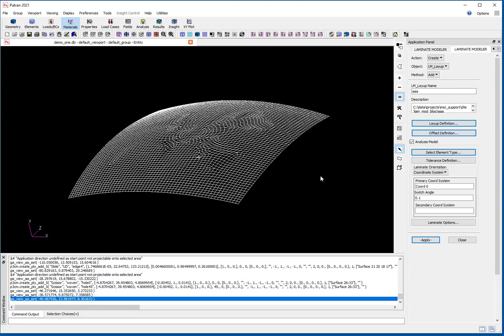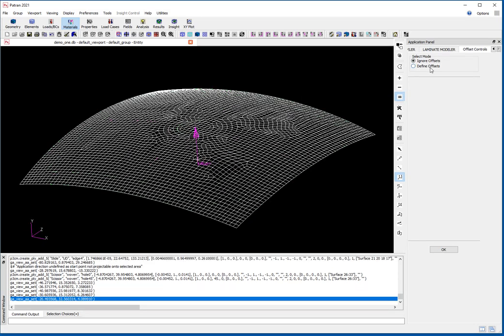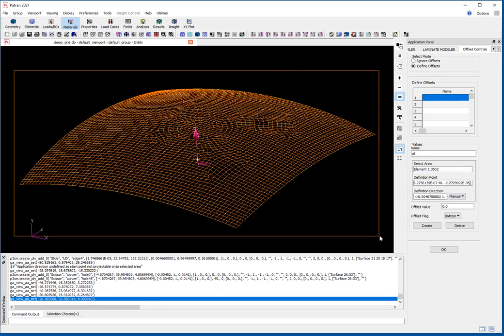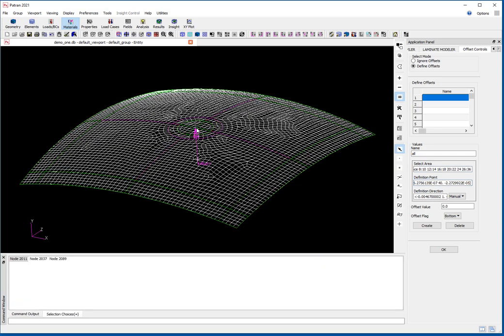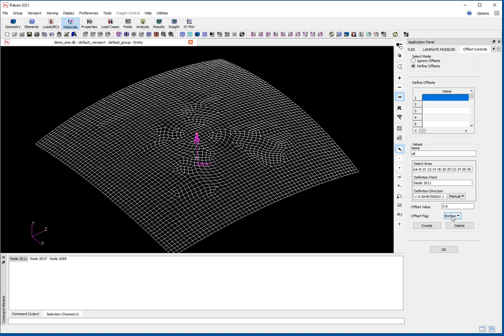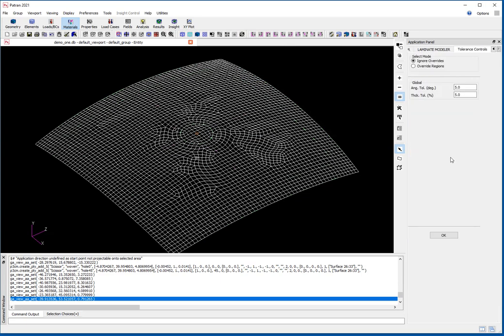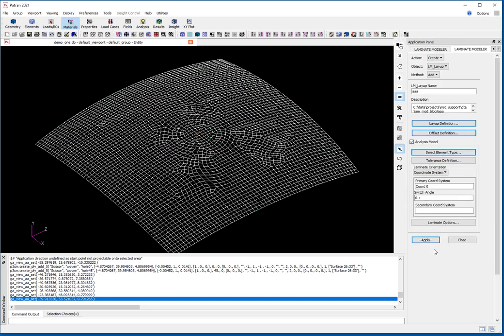I'm ready to create my finite element model. I can define the offset — I want the whole model with the definition point in the center, and based on an offset in that direction I want that to represent the bottom surface, so things stack away from it. I can then set the element type and the tolerance definition, which controls how closely we group orientations. If the difference is less than 5 degrees, they're treated as nominally identical. We can tighten or loosen that as needed. Then I hit apply.